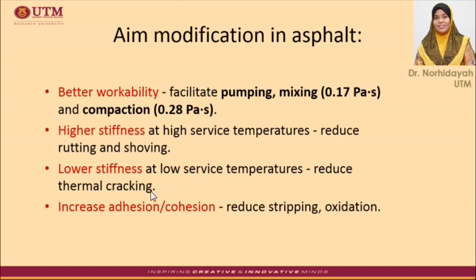Next is to have a lower stiffness and faster relaxation at low service temperatures in order to reduce thermal cracking or low temperature cracking, among which the relaxation time is of importance for the characterization of asphalt binder at low temperature. The physical meaning of relaxation time is the characteristic time for a system to reach a stable condition after a disturbance, or in simple words, to recover from the stress. The longer the relaxation time of asphalt binder at low temperature, the longer time is required for the asphalt system to dissipate the total stress.